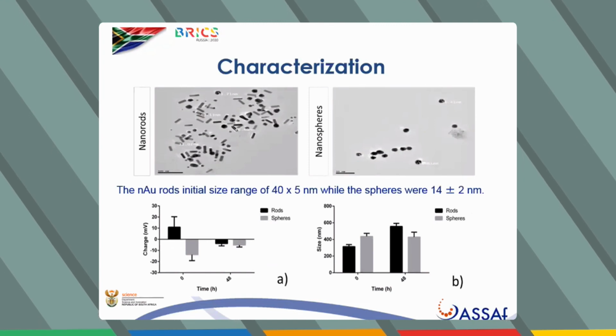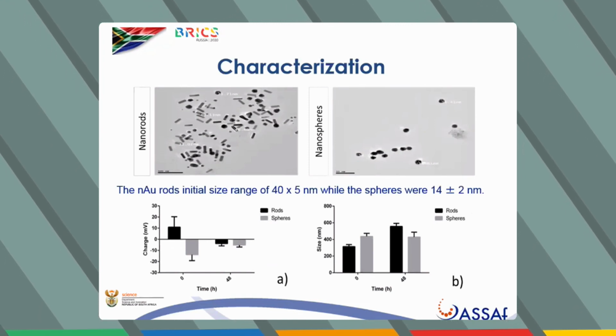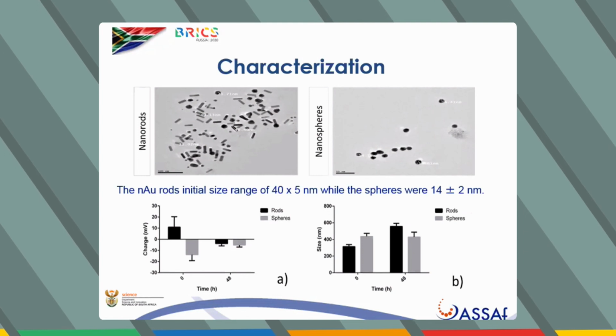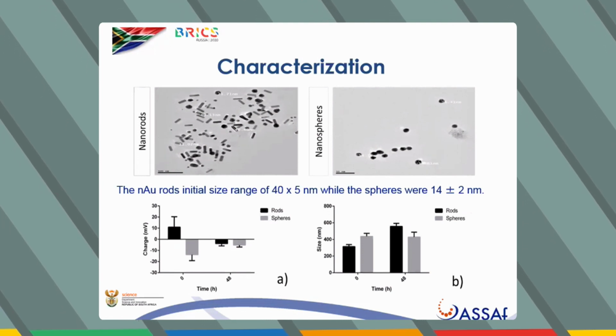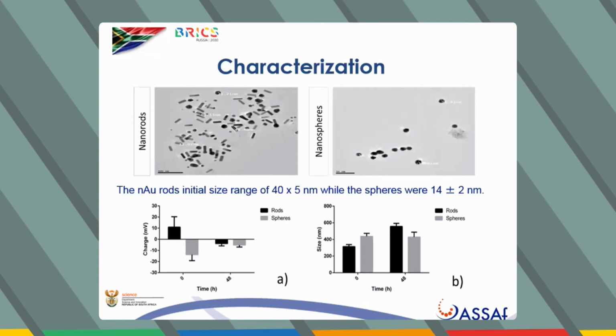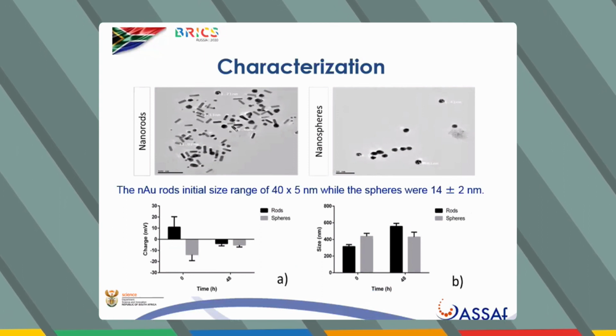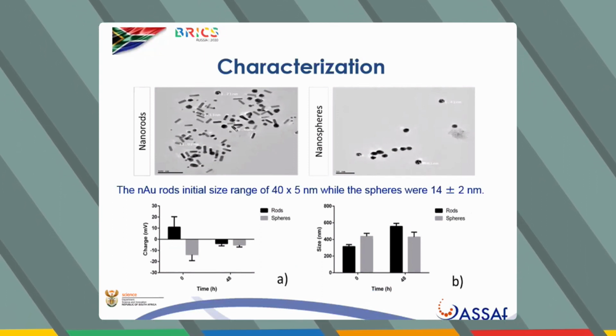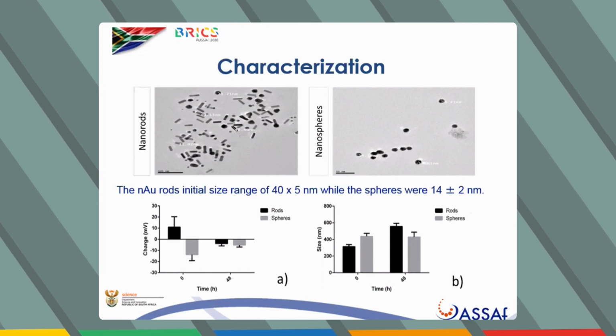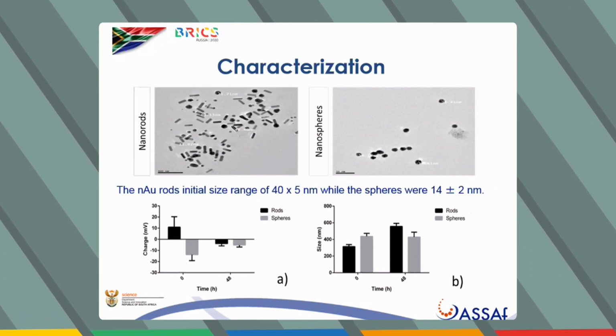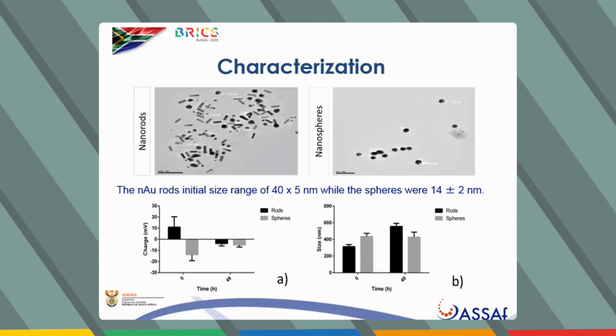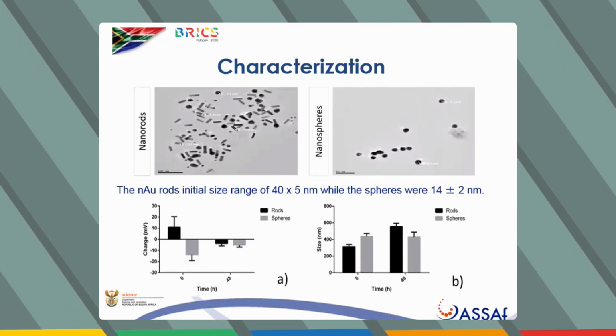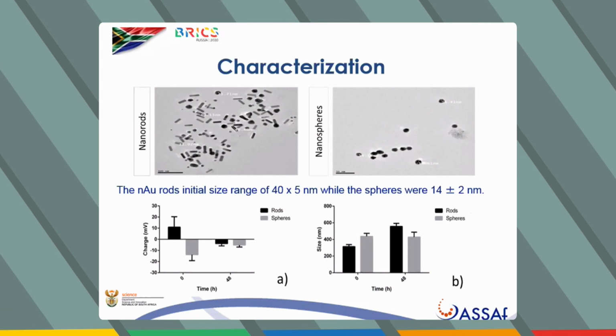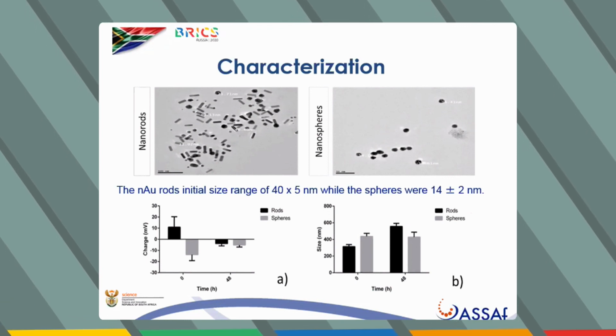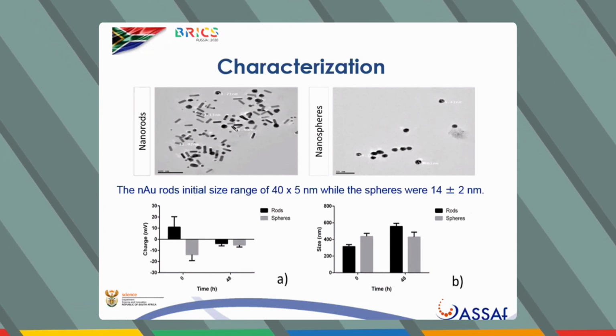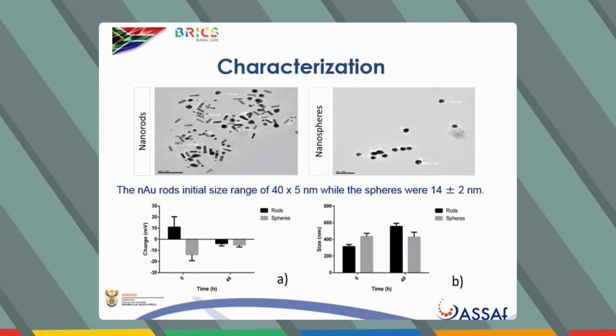So just to look at the basic characterization, I can't go into much detail here, but when we looked at the nanorods under TEM analysis, we could already see that even though they're called and marketed as nanorods, there are also spherical and star-shaped particles present. However, the nanospheres remain quite constant in terms of their production and what we were able to see. And based on the zeta potential, we also saw that there was some kind of interaction with the medium. And as I said, we were expecting this already because there are several salts present.